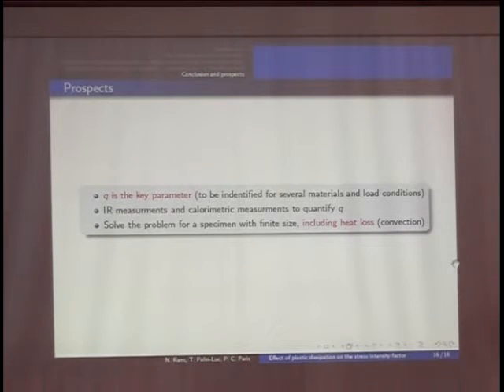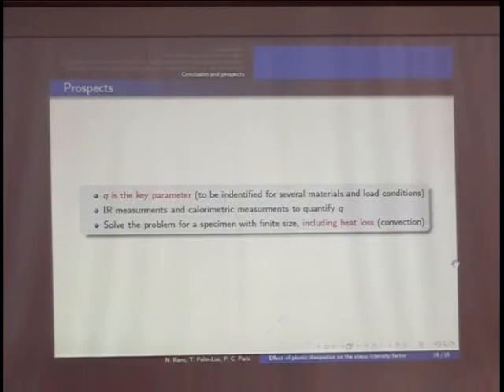But if we look at that, I think that, of course, maybe many things are in this parameter, but up to now, we don't know how to estimate its value without experiments. And about the experiments, you say that it's difficult to measure the strain energy, the plastic strain energy. I think we have to discuss, because according to me, you do not measure the plastic strain energy. What we can measure with infrared measurement is only the temperature, and we can compute. Yes, you can compute. You need a model to estimate the plastic strain energy. And I think in this model, absolutely correct. Yeah. But in my model here, there is only the physical parameter, which is Q. But it's clear that in this model, I do not say that Q is related to the plastic energy or to another phenomenon. I think after we have to go deeper in the constitutive behavior of the material. Okay. See.